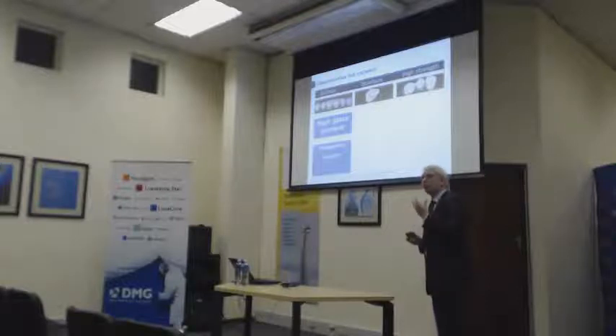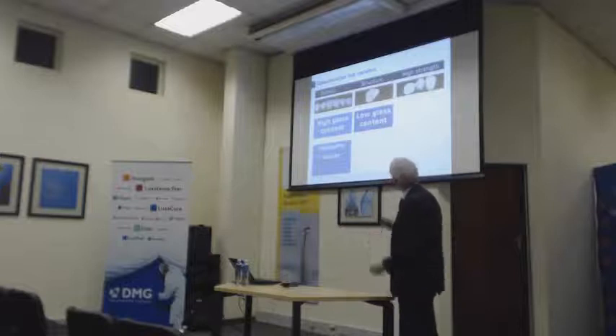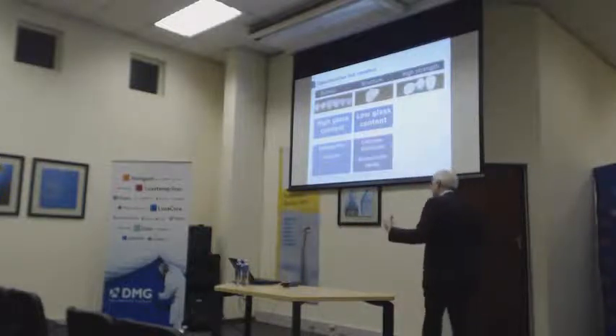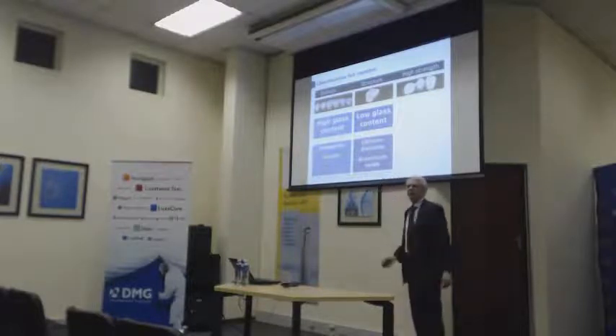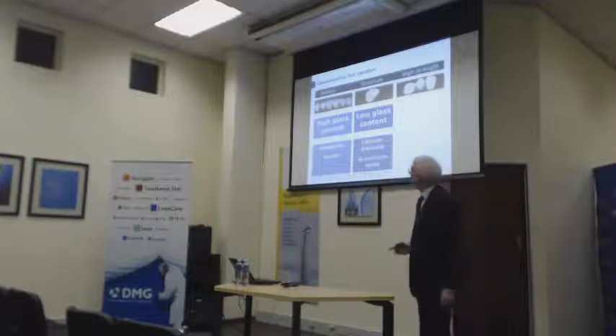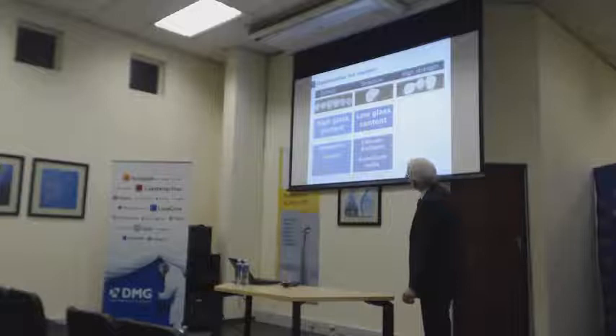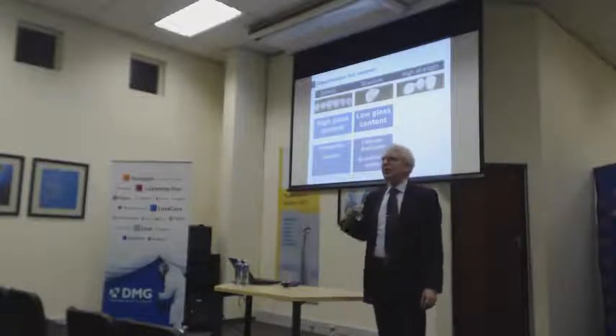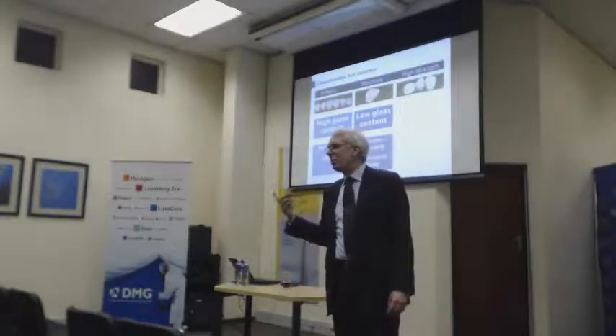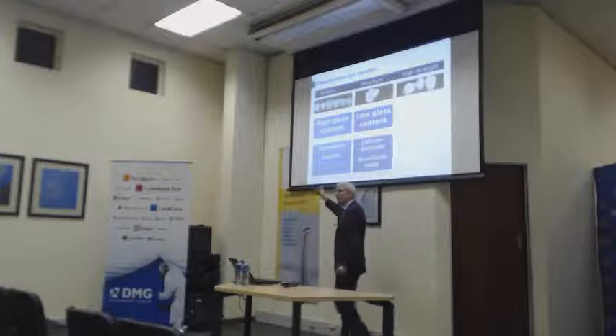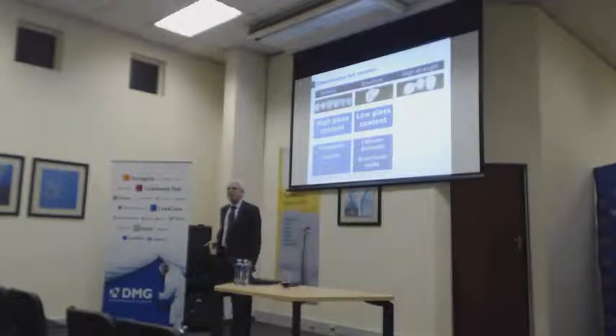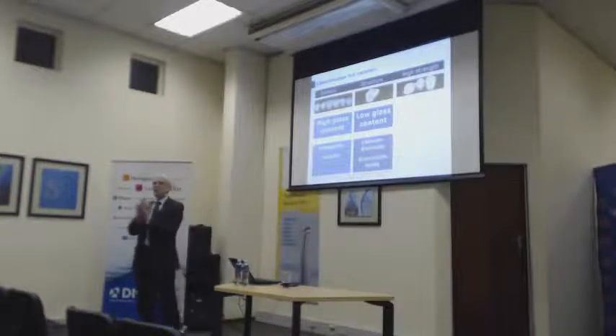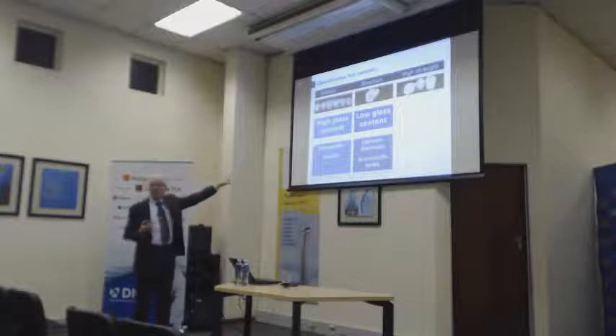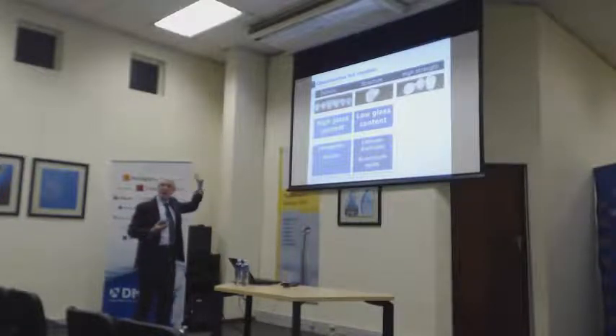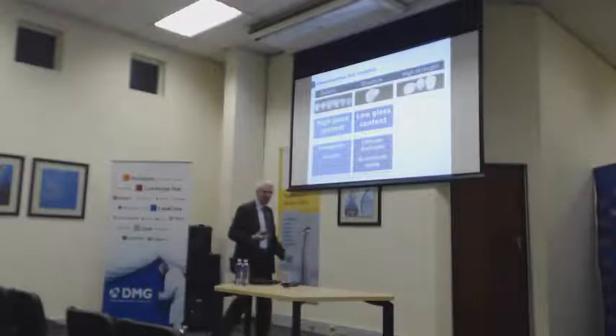And then we have what's called structural ceramics. And this is the new kid on the block. This is low glass content. This is lithium disilicate. To some extent, even In-Ceram. I don't think In-Ceram is being used very much nowadays anymore, but that would be also something like this. And these structural ceramics, they tolerate being cemented with these self-adhesive cements. This works. If you try to use aesthetic ceramics with self-adhesive cements, they will probably fail and break, because the cement needs that absolute stress transfer that is only achieved if you silanate the ceramic, if you cement it with a resin cement, and then bond it to the tooth structure. This is what you need.